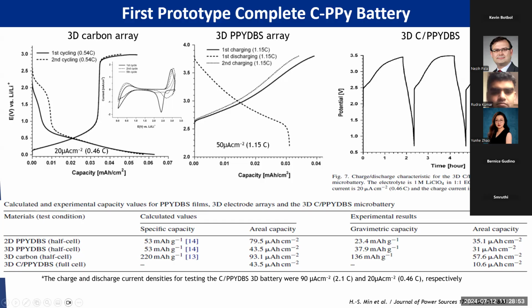But when we look at a full cell, we charge the carbon first, then we remove the lithium metal, then let the carbon have the lithium ion inside, then do the discharge process with a counter electrode as polypyrrole. Now we found out the performance is really bad. How bad is it? If you look at the area capacity, because it's hard to estimate the total weight, it's on chip level, already on silicon wafer. So we found out the area capacity, ideally, by the calculation, we assume it's 43.5 microampere hour per centimeter square, but in reality, we only get 10.6 microampere hour per centimeter square.